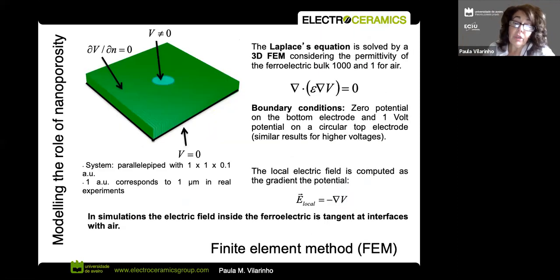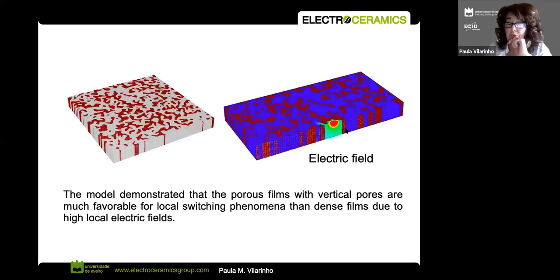And okay, so we continue doing a little bit more finite element modeling. The first one was Monte Carlo simulation. The second one was finite element modeling. And what we were really understanding is that the model demonstrates that the porous films with vertical pores are much more favorable for local switching than the dense films, due to the high electrical fields. So the high electrical fields are really helping the switching.